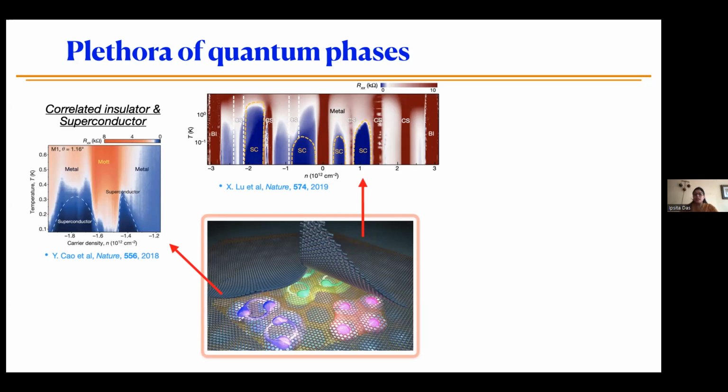So what they did in the end is that they first cut the graphene so that you can completely separate them out. So when you are picking up one layer of graphene, you are not rotating them. So you are not putting any strain on the other layer. So you pick up one layer cleanly and then you rotate the other layer and pick it up.